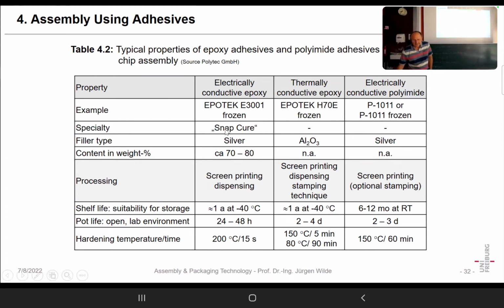So here we can say we have the silver powder, and it has 70 to 80 weight percent of silver flakes in. It can be put on the substrate by screen printing or stencil printing or by dispensing with a needle. And there are several aspects which are important.